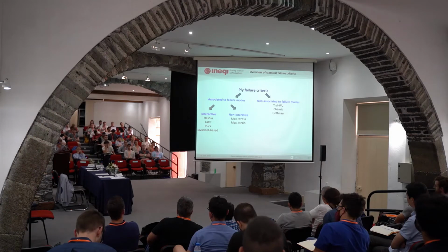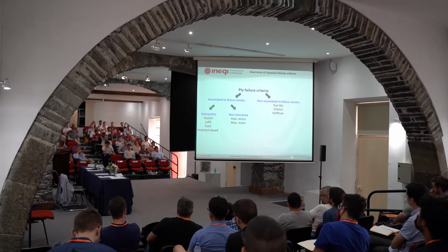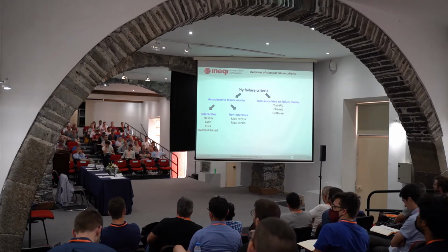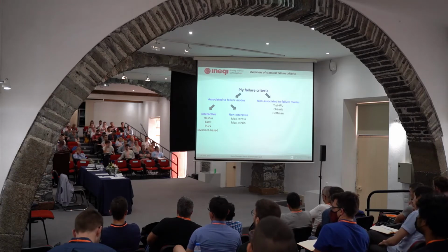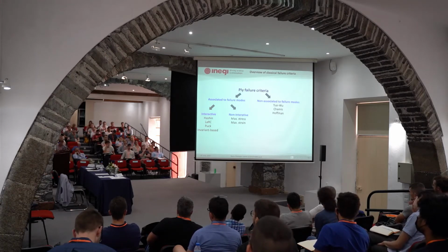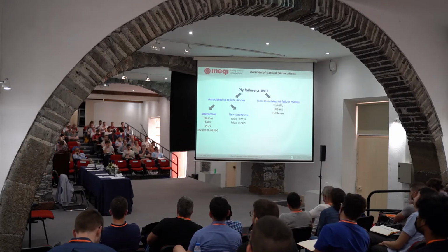If you have stress gradients, and if you have multidirectional composites, as normally you have, you need to combine failure criteria with the damage model. Otherwise, you are predicting the first crack, but then the specimen will take higher loads. So this is the first thing that we need to understand. This is something that you need, but alone it's not enough.